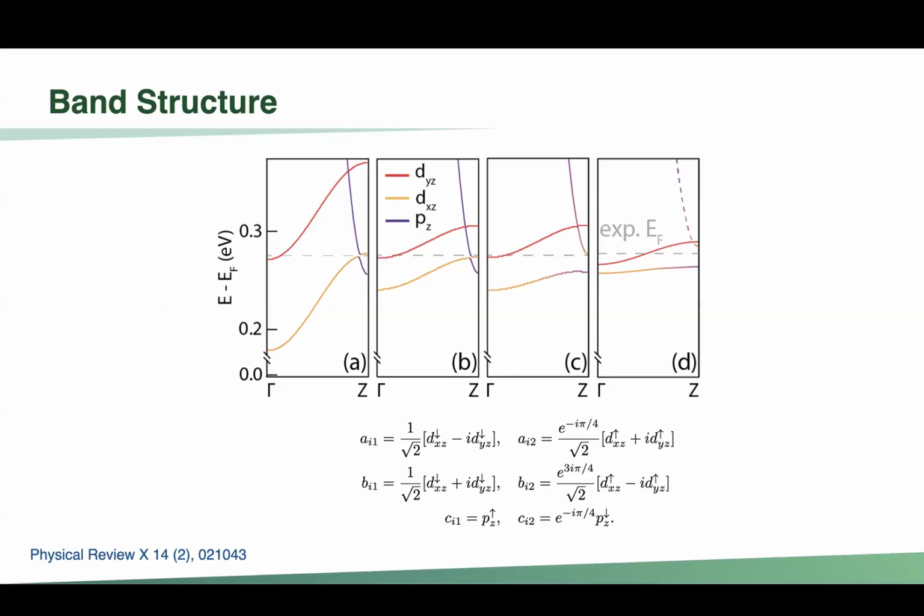So first, and this was the input of CX again, he wanted to have all the terms that accompany the spin-orbit coupling together and play with the spin-orbit coupling constant. So we did that, and it happens that if you increase the spin-orbit coupling by 1.5, you get the renormalization of the bands closer to the experimentalist.